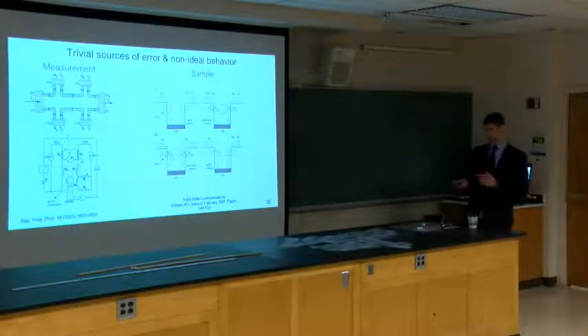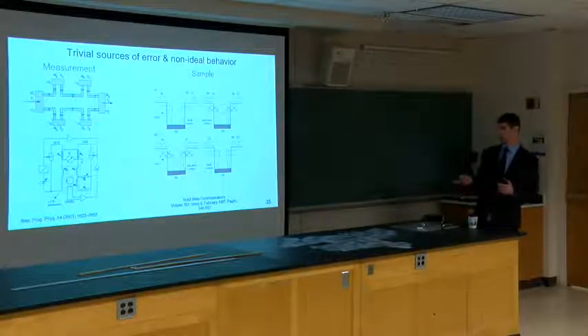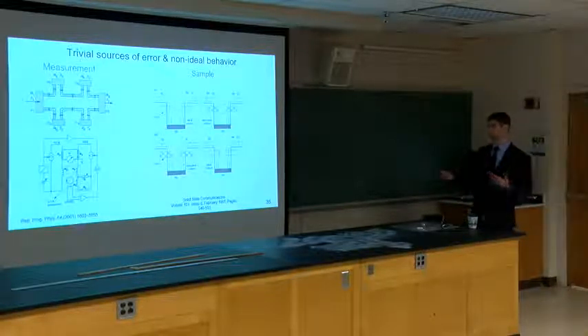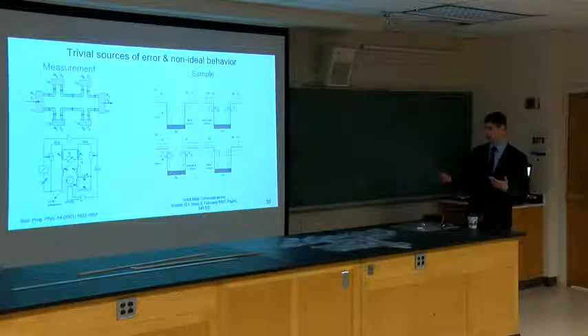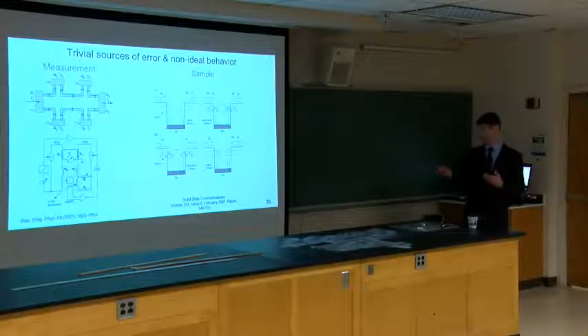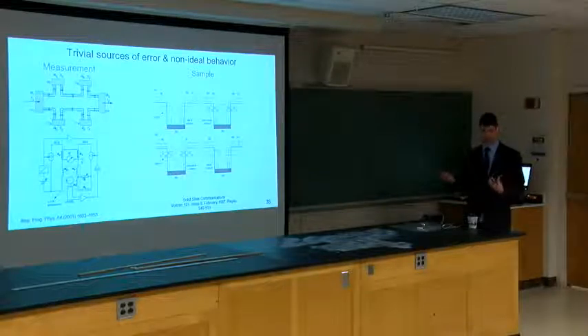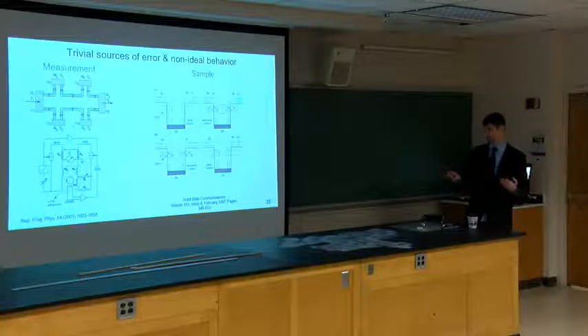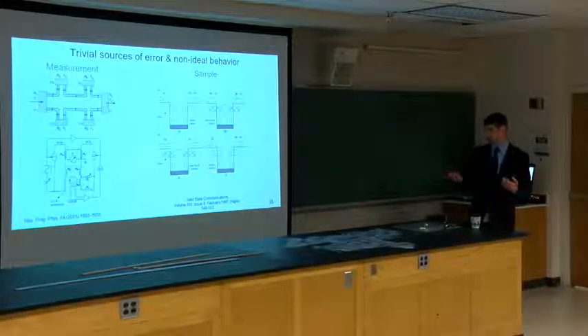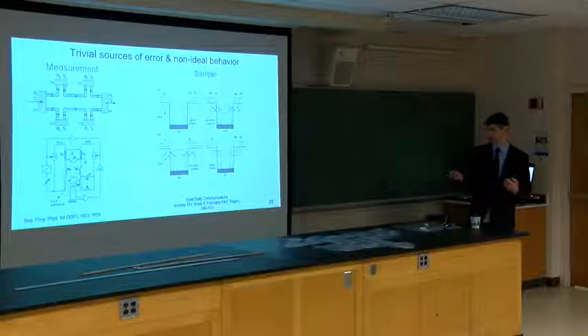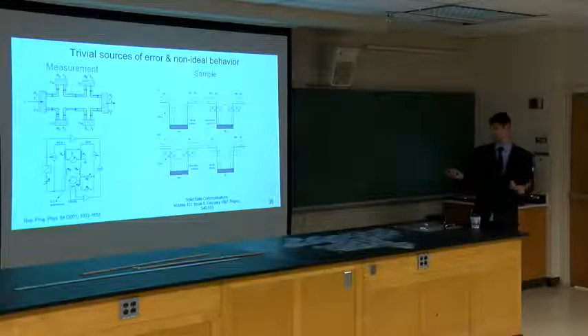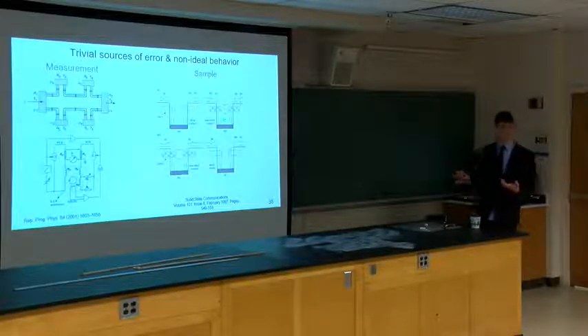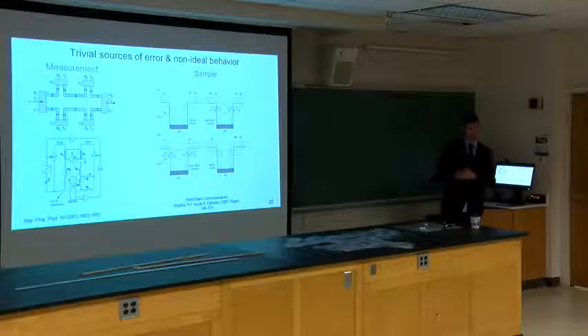The other trivial example would be that if your contacts, so this region right here, are not designed properly, whether it's too small or you have some outside electric interference or a particle, say, on 2 of the edges, that's somehow modifying the electrostatics in those areas, you can basically cut off these edge states. So instead of getting something like this, where those edge states flow from the contact out, you end up having an edge state that is just within the contact. And in this case, if you measure the voltage, you'll just be measuring the quantum Hall state of the contact and not the bulk.